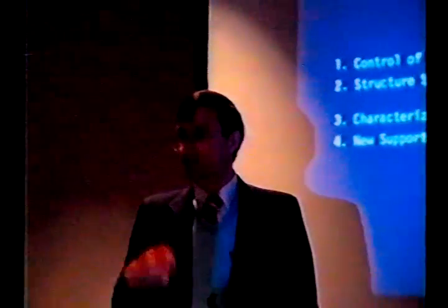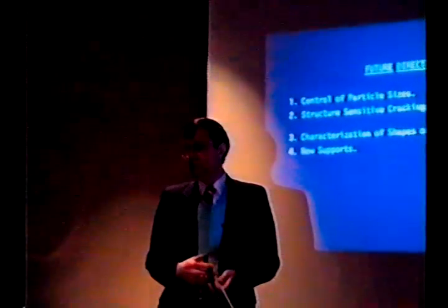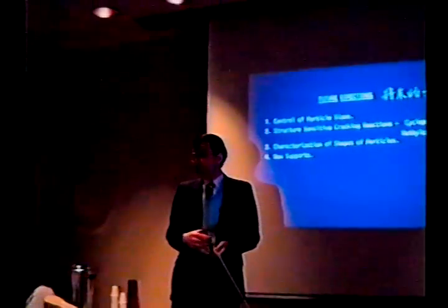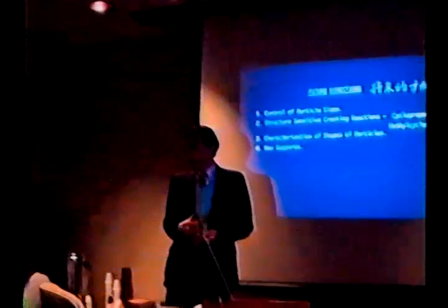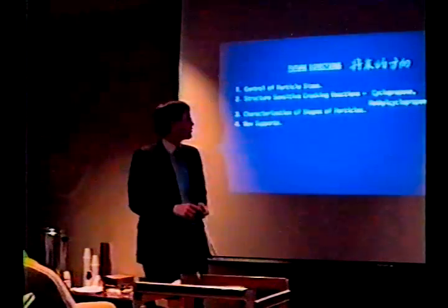One of the real key things here, to fit these data, which don't fit too well at low temperatures, is the size and shape of the particles. We've got to have some handle on what they really look like. Maybe they're 5 angstroms, or they're flat like a raft, or what do they really look like? We've used some of the world's best TEMs, and we just can't see these particles. They're just so small. Maybe they're inside the pores. How can we get a handle on what the sizes and shapes of those particles are?